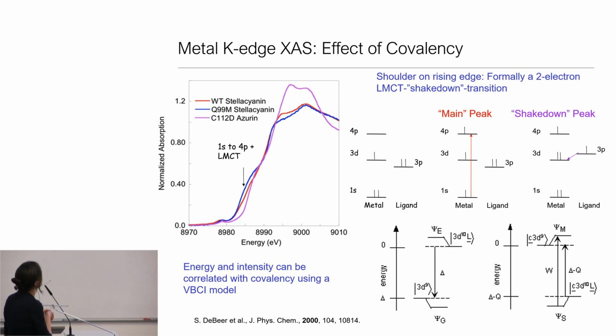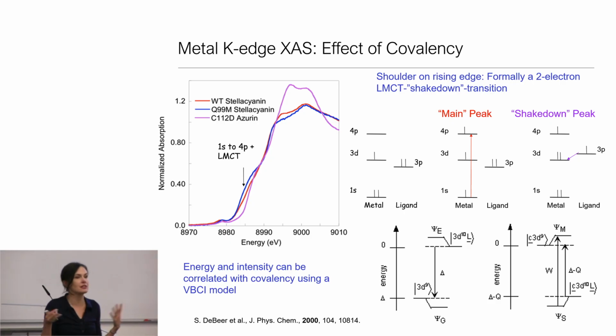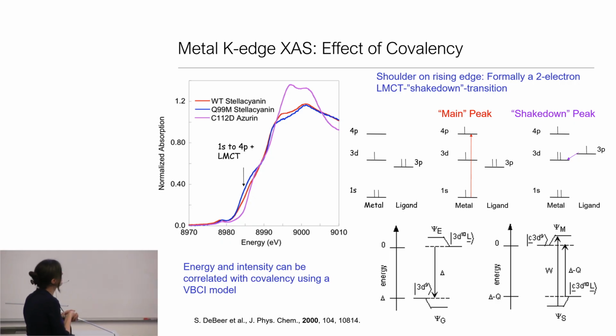But what you see is these are 3 related copper K-edges where the onset of the rising edge actually changes. And I won't go through this in detail other than to say the nature of just one ligand was changing. And the way we interpreted this was that this was a so-called shakedown feature. And this is similar to ligand to metal charge transfer or shakedown transitions that you might see in photoemission spectroscopy. It's just the idea that after this initial metal 1s to 4p transition, it can be possible that due to the increased effective nuclear charge that results from this core hole, that this 3d can actually relax below the level of 3p, making an LMCT event favorable.